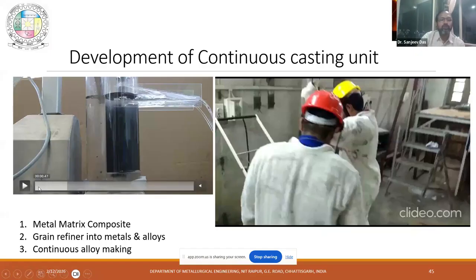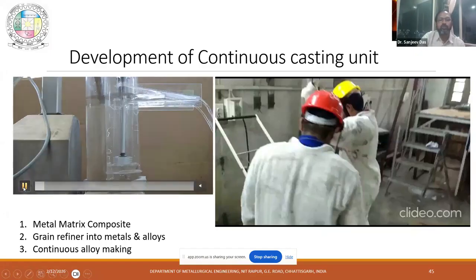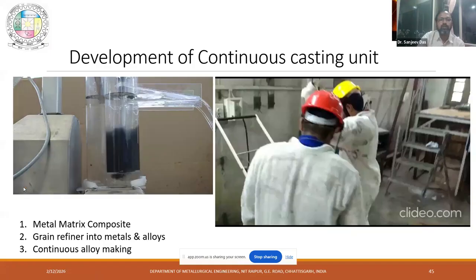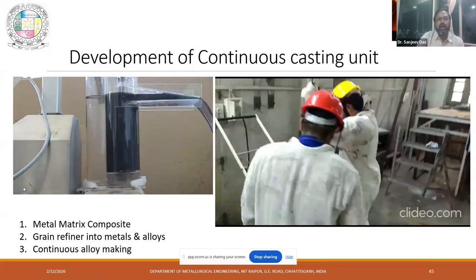And when you see the video from the starting, there is no vortex formation at the top. So any particle you add, it is going to mix very nicely. And when you are doing it, you can see it is a continuous process. You don't need to do batch type; you can add as much particle, as much liquid metal in it, and you can do it.